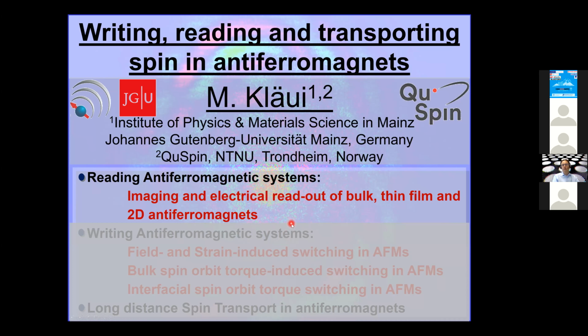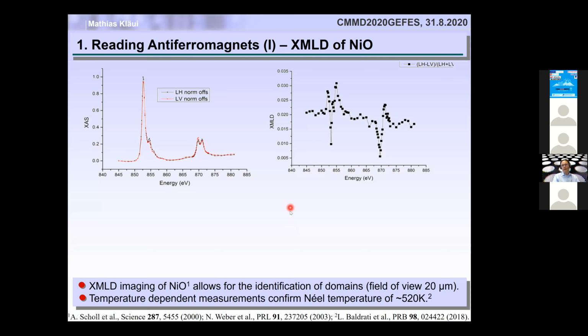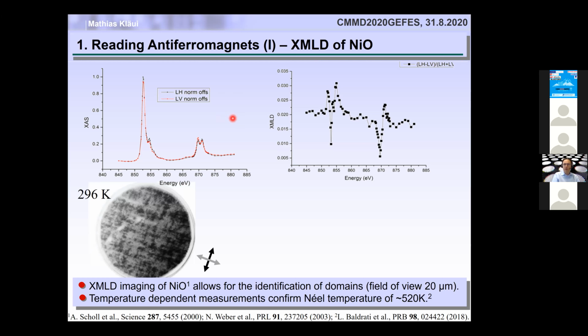So first, in order to make such an antiferromagnet useful, we need to be able to read out the information. So how can we do that? One way is so-called X-ray magnetic linear dichroism. X-ray magnetic linear dichroism means that if you have linearly polarized X-rays for a certain energy, then the absorption of these X-rays depends on the alignment of the polarization of these linearly polarized X-rays and the direction of the two sublattices, the so-called Néel vector. So if we have these two sublattices, then the difference between these two sublattices is the Néel vector. And this allows you to actually image magnetic domains.